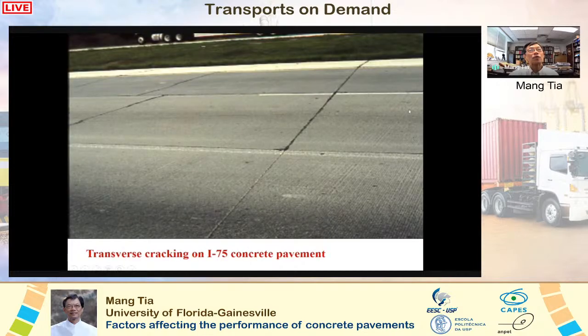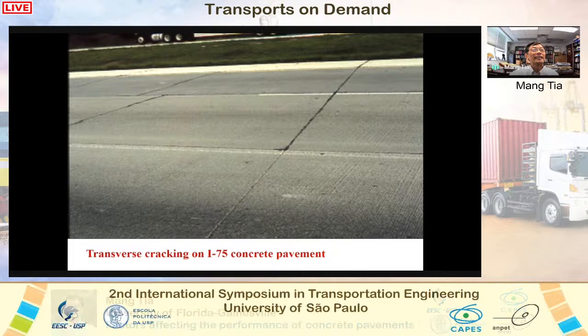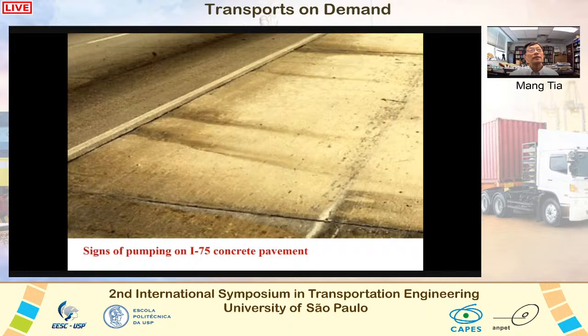Soon after the highway was opened to traffic, transverse cracking was observed, especially on the longer slabs. Later on, when structural analysis was performed to evaluate the effects of skew joint, it was found that the use of skew joint didn't really help. It actually increased the maximum stresses due to the acute angles of the slabs at their corners. And also pumping was observed from the supposedly non-erodible Econocrete base.